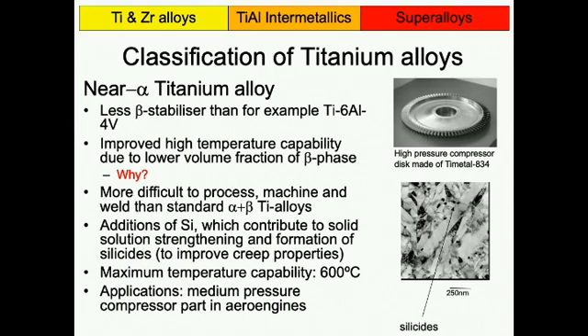And because you have rotating parts, you might also use 834, one of these near alpha titanium alloys, for the blades, where you have the highest temperatures. So the temperature actually rises from the center to the outer part, not just along the engines, but also radially all the time. And if you now have the blades rubbing against the casing, at very high temperatures, titanium can ignite. And having fire in an engine is not a good idea. Really not. So that's the other reason why at some stage all this development of very high temperature titanium alloys stopped, because it was recognized you just can't go beyond 600 degrees C.